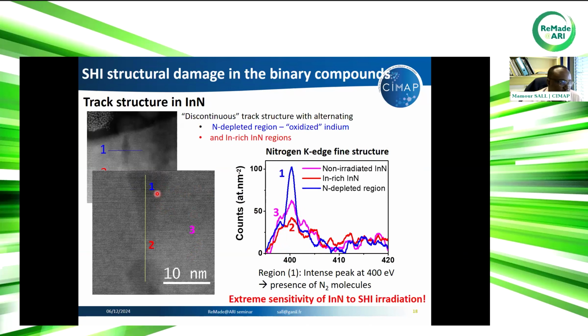So this is to say that indium nitride is extremely sensitive to ion irradiation. The material dissociates. We have different regions along the track: an indium-rich indium nitride region, and a nitrogen-depleted region containing nitrogen bubbles inside.